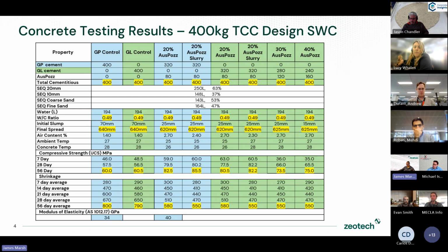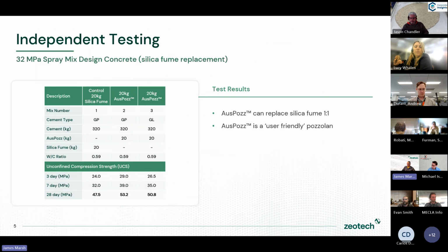We never expected to get such high strength gain and such low shrinkage. I think that's just an effect of making sure that we engineered this AusPozz material exactly right for concrete. And in fact, we got such a high purity kaolin feed. This kaolin that we use as our feed, which comes from Queensland, is probably the purest I've seen anywhere in the world as a naturally refined kaolin out of the ground. And that converts directly to pozzolanic reactivity, which is what we're seeing there.